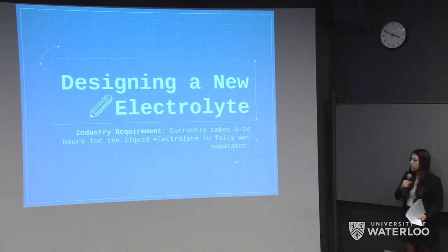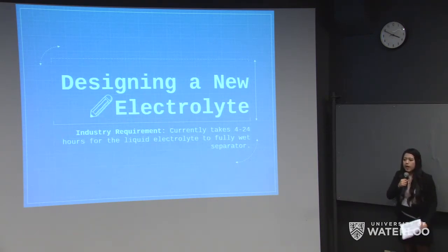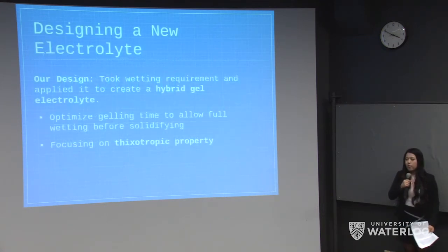So in fact, industry data tells us that currently it takes 4 to 24 hours for the electrolyte to fully wet the separator, and this broad range is due to the fact that there are many different sizes and types and thicknesses of the separators. So with this 4 to 24 hour knowledge, we applied it to design a hybrid gel electrolyte.